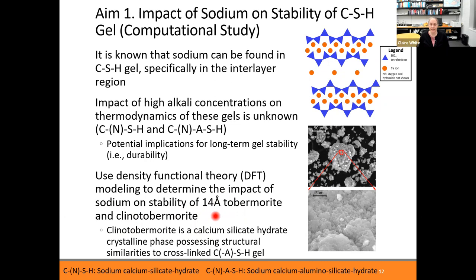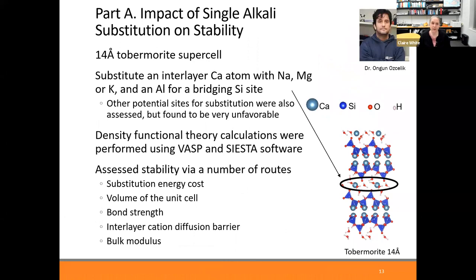And we've also used another one known as clinotobermorite. For 14 angstrom tobermorite, the structure is very similar to CSH gel, but these silicate chains are infinite in length. They're not chopped up like they are in the CSH gel. So that's the main difference between the two. What we did in this study was we substituted the calcium atom in the interlayer with different atoms. And also we looked at the change in the thermodynamics of the system when we put aluminium in on one of those bridging sites for the silicon. We also assessed other potential substitution sites, especially for the sodium and potassium, but they were found to be very unfavorable. These calculations were done using plane wave calculations, specifically VASP, and also the Siesta software.